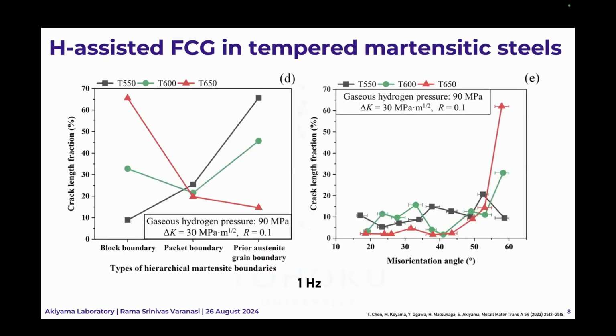So this is for the purely tempered materials, by Dr. Chen. And if we look at this condition where we have a frequency of 1 Hertz, the prior austenite grain boundary fraction is about 45 to 50%.